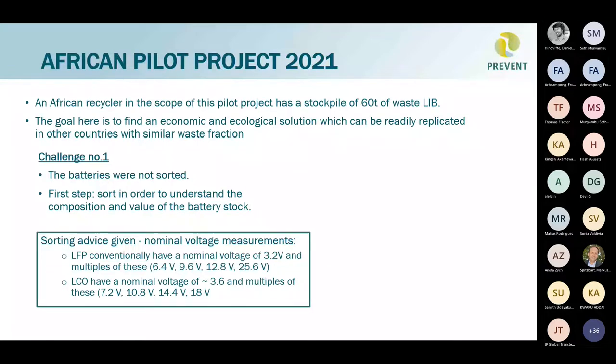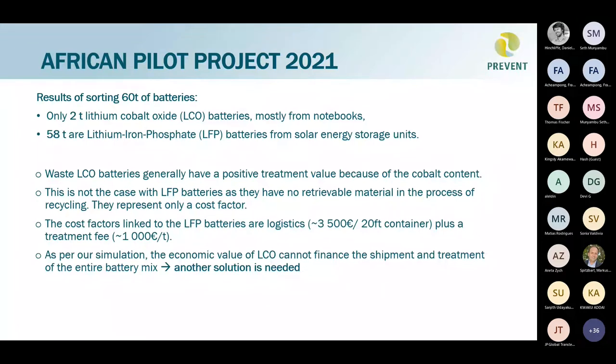The results they got from their sorting process was that only 2 tons of lithium cobalt oxide batteries, mostly from notebooks, were present inside the pile. And the rest was 58 tons of phosphate batteries from solar energy storage units. I said already that batteries with cobalt have a positive value. So it was good news for 2 tons, but sadly, I guess everybody would have hoped for the reverse in the numbers. Because the lithium ferrous phosphate batteries